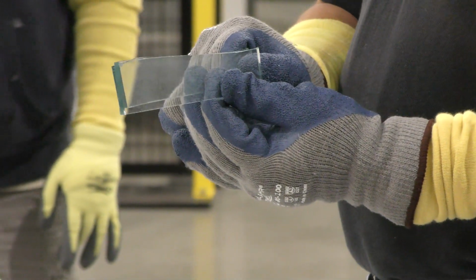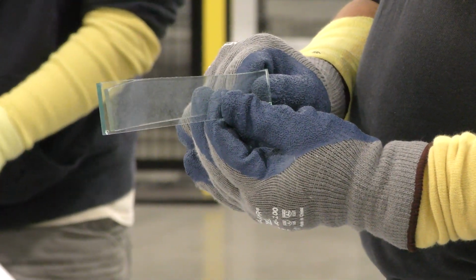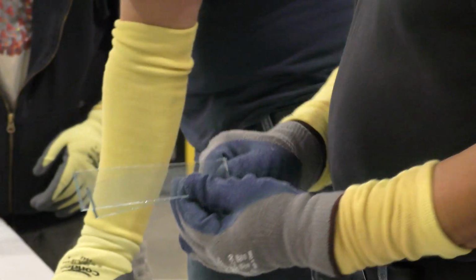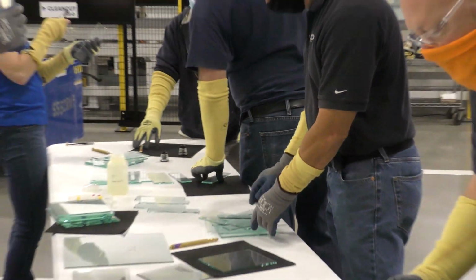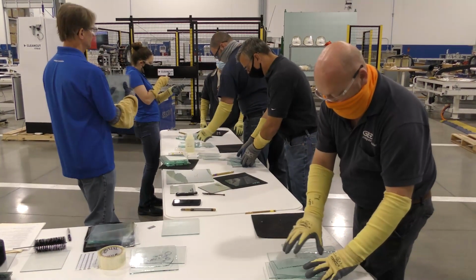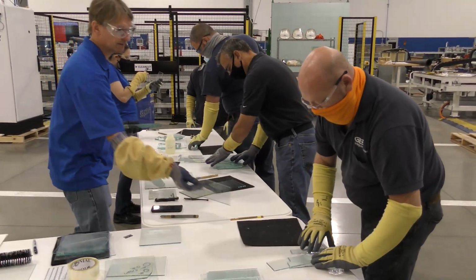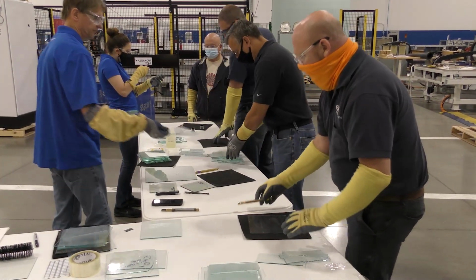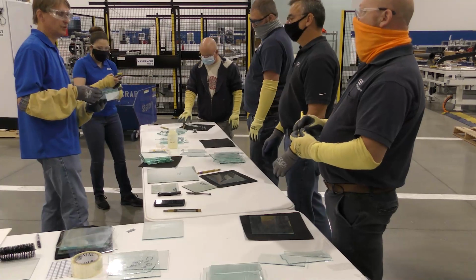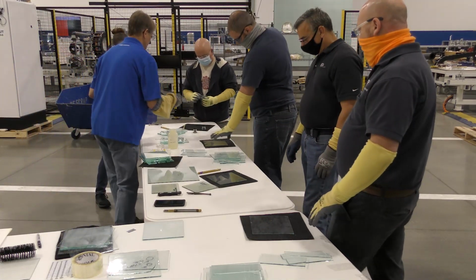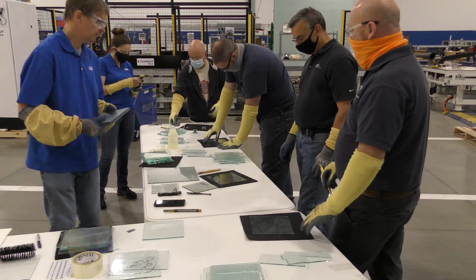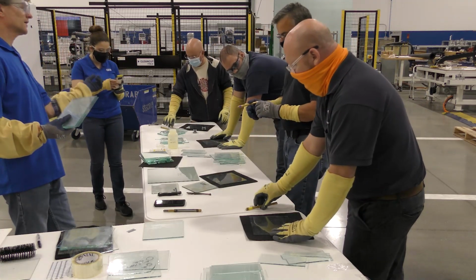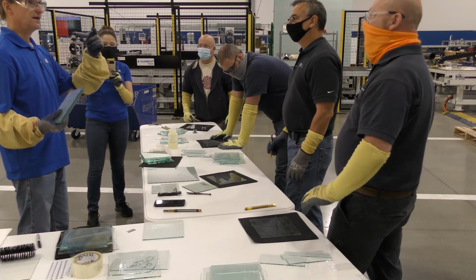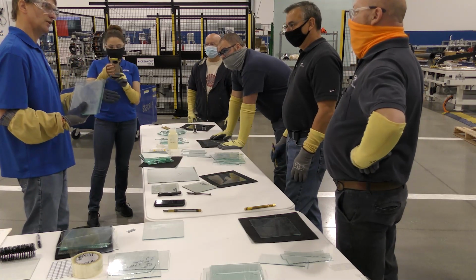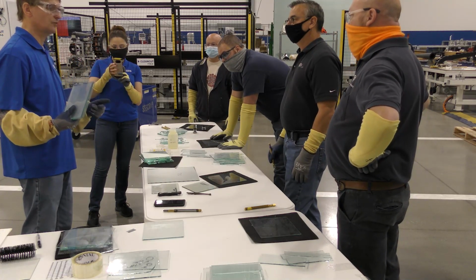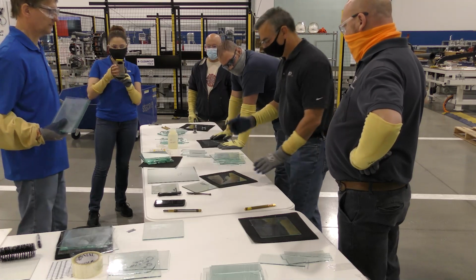All right. So now we've done a lot of work with 5mm glass. So push all that to the side. I got some pretty common 2.5 mm. We call it single strength glass, but it's 2.5 mm glass. This is half this thick is what you've been working on today. And what you do is use the purple wheel. So for thick glass, I had you using a sharp wheel angle. Now for thin glass, I want you to use a blunt wheel. So do the same thing.